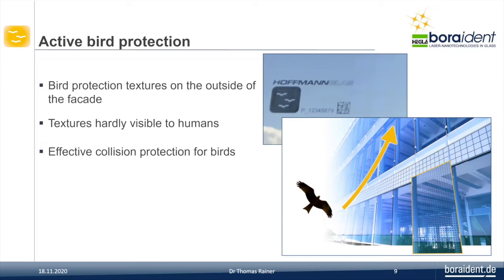One possibility is if you have a coating on the outside, on position 1, maybe a pyrolytic coating, an easy-to-clean coating or something like this. Then with the laser, you can remove the coating and make a pattern inside this coating. It's possible to see here circles in the photograph made by laser, and this pattern is very easy for the birds to see, because birds see more than we humans. They see in the UV region too. And for the birds, the contrast is nearly black and white. And so the birds see this glass pane and avoid hitting it.